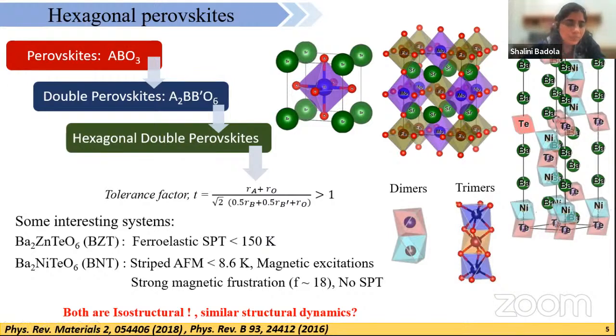BZT undergoes a structural phase transition from a high temperature trigonal to a low temperature monoclinic phase below 150 Kelvin, while BNT exhibits an antiferromagnetic transition below 8.6 Kelvin along with a strong magnetic frustration. One interesting point to note here is that despite being isostructural to BZT, it does not show any structural phase transition. So this raises the question: what makes the structural dynamics of nickel, or BNT, different from BZT so that it doesn't undergo a structural phase transition?